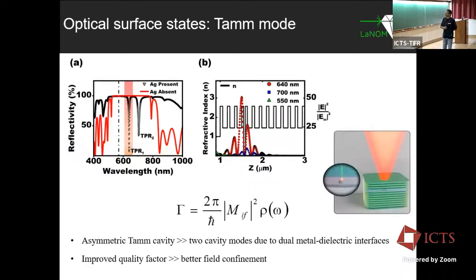We simulated this, mostly done during COVID time. We tried to get a Tamm mode at 640 nanometer, but we also got another state, another Tamm state. Why do we get this? Because there are two interfaces: there is a dielectric interface from the metal, and there is a dielectric interface from the top mirror also. So we expected, yes, we do have two states.